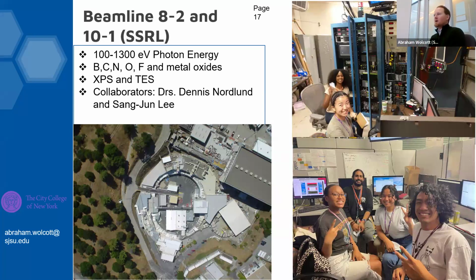The energies of the incoming photons are between 100 to 1300 eV, giving us access to all the low Z elements: boron, carbon, nitrogen, oxygen, and fluorine, as well as metal centers. On the right-hand side are pictures of my researchers controlling the experiments at beamline 8-2 and 10-1.